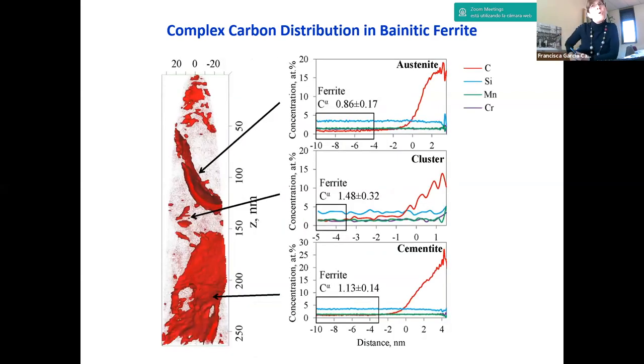For so long, it was not easy to measure the carbon content in the bainitic ferrite locally, away from carbon enriched regions. At the very early stage of our 3D atom probe work, we determined carbon content with concentration profiles and proxigrams. Like in this example, you have a reconstruction with a lot of carbon accumulation: carbon enriched austenite, cementite, carbon clustering, and always at the other side of the interface, there is ferrite. Then we move away from the interface and determine the carbon content. But is that the carbon content in solid solution? With time and a lot of results, we found out that it's not easy to measure the carbon content in this material with that level of carbon accumulation at the nanoscale.